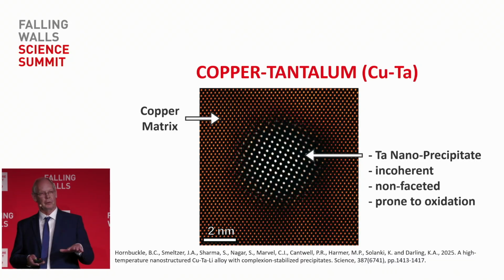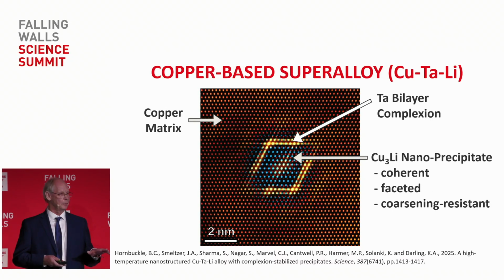So we further modified this composition to add lithium, particularly because it prevents the oxidation. Lithium is a very strong reducing agent. And it produced an incredible transformation in the microstructure of the material.